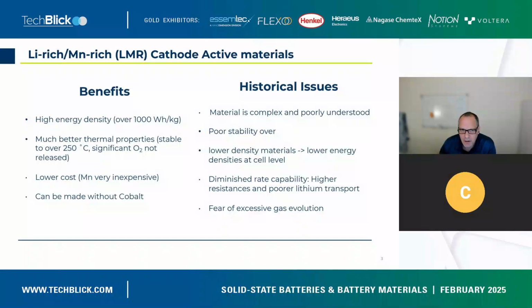And the benefits are clear. It's super appealing that you can have very high energy densities, over 1,000 watt-hours per kilogram at a material level, demonstrated many times over. It's got good thermal properties. It's typically stable to a pretty high temperature, even when fully delithiated, higher than the nickel-rich materials. And a lot of oxygen is not emitted. When it does, they're really decomposed. So it's got some safety advantages, more similar to LFP. It's lower cost if it's manganese-rich and nickel light and has no cobalt. There's a lot of promise there.